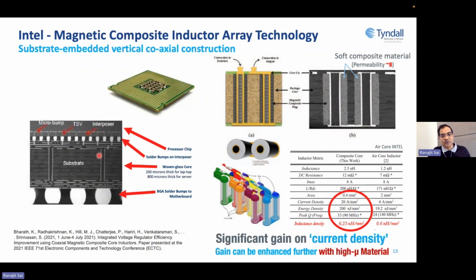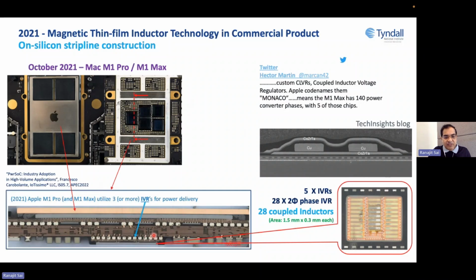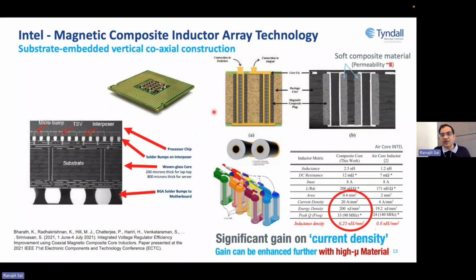What they have done is they have used the thickness of the package, and there are these plated through hole via structures. If I go back, you could see this package structure has these different vias from top to bottom, plated through holes. So something like this. And they use this plated through hole surrounded by a magnetic material as an inductor. So they are hiding their inductor inside the package substrate. When the signal is going from below to above, PMIC to the load, on the way the inductor is fabricated. That was a very clever solution, and it has shown a huge benefit.